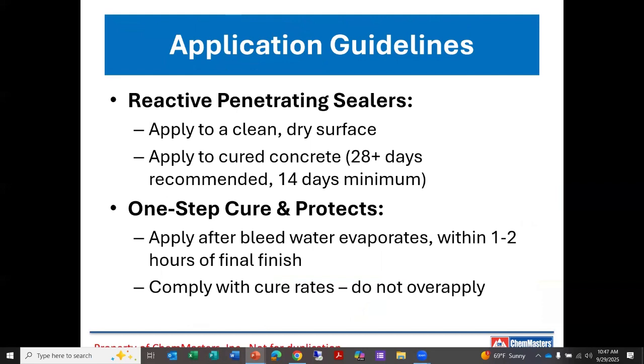So when we're using reactive penetrating sealers, we want to apply to a clean, dry surface. Apply to a cured concrete. Recommended 28 days, but 14 days is a minimum. Our one-step products you can apply immediately after the bleed water has evaporated, within an hour or two of final finish. As soon as you get that final finish on, particularly with type 1L cement or concrete produced with type 1L cement, where we're worried about that early desiccation at the surface, get it on as soon as possible. Comply with the cure rates. Don't over apply. I think that's something you hear about with anything that is particularly a decorative product. More is not better. More creates problems of its own, and we don't want to get into those.